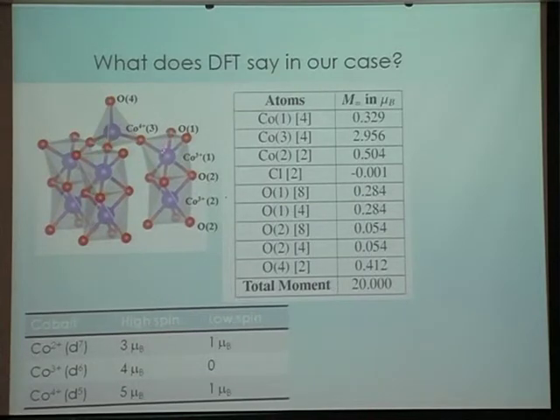Now I remind you once again that the nominal expectation was this is cobalt 4+, this is cobalt 3+, these two are cobalt 3+. Here for easy reference, I have just given the expected moments that would come if you have cobalt 2+ in high spin and low spin, cobalt 3+, high spin and low spin, and cobalt 4+, high spin and low spin. Now look at this table.